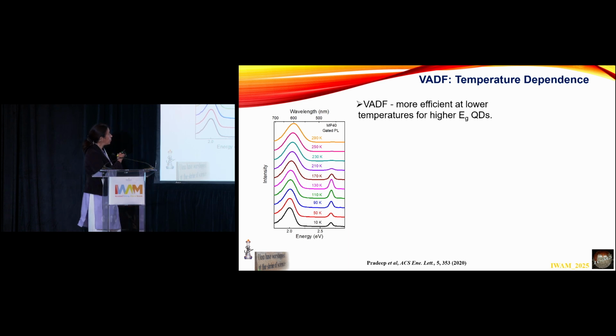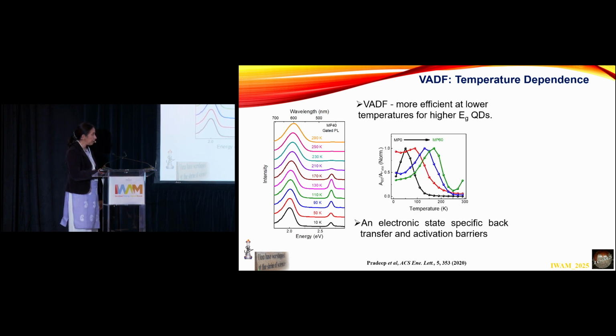And sure enough, you see that if you take a compound which is, when I say 40, I mean 40% chlorine and 60% bromine, at room temperature there is no excitonic emission, and as you go down in temperature, you see that there is this band edge emission. If I look across all of the temperatures, I can see here that at a particular temperature, it starts to go up very strongly, and that is dependent on the band gap.